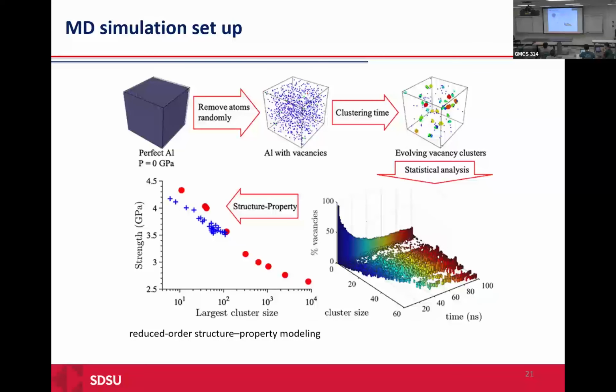Let's see what we can do with the MD simulation for this process. We started with a perfect aluminum crystal and then randomly removed some percentage of atoms to give some percentage of vacancies to the structure. The second figure is the sample, where those dots are showing the vacancies. For the purpose of visualization, I removed the rest of the atoms and just show those vacancies as points.